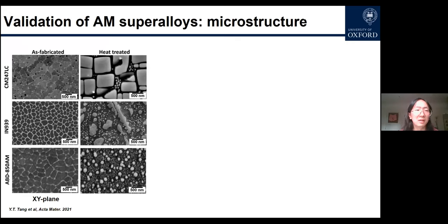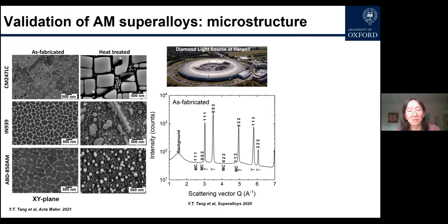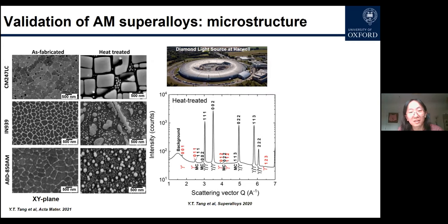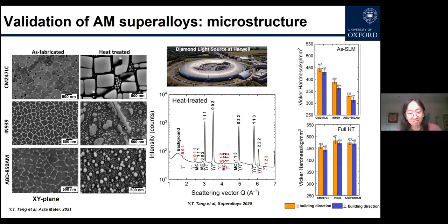This is basically the superalloy microstructures. Very interestingly, you can see there's no gamma prime in the as fabricated state, or as printed state, but it can pop up after the heat treatment. We didn't really believe this in the beginning until we performed some synchrotron studies at Diamond Light Source, which is actually down the road, about 20 minutes that way. In the as fabricated state, you can't see gamma prime by resolving the superlattice peak, but you can after heat treatment. This is also reflected by the heat treated hardness compared to the as fabricated hardness. You can see the gamma prime really has increased the strength of the material.